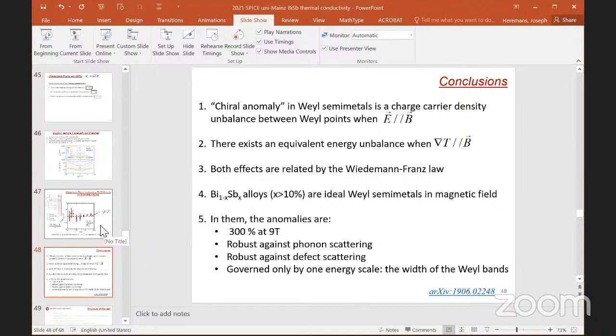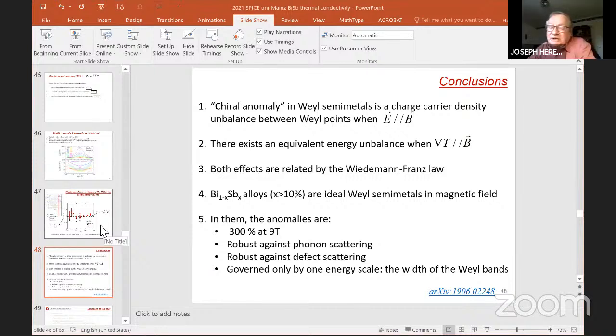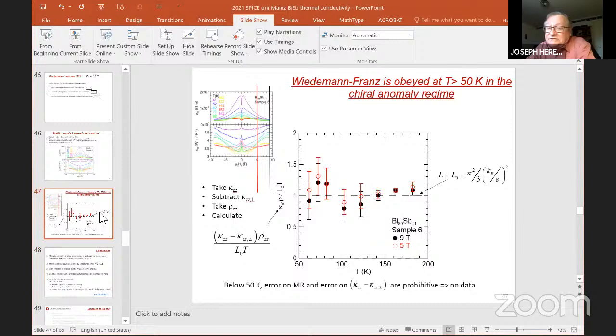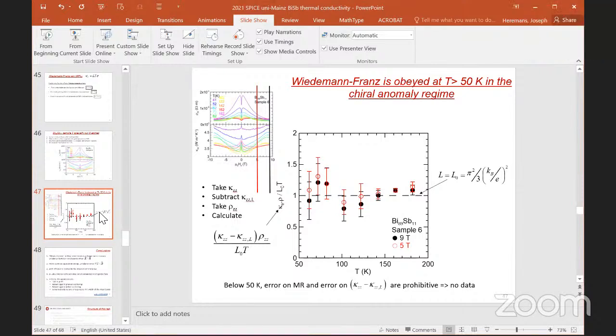No, it really depends. It was initially found in 1954 on a classic semiconductor, n-type indium antimonide, so it's completely in a diffusive regime. It is totally general. It's a macroscopic effect. It's just the current lines that get distorted. But it holds in general when omega_c tau is much larger than one, this will dominate your measurements. Okay, thank you very much.